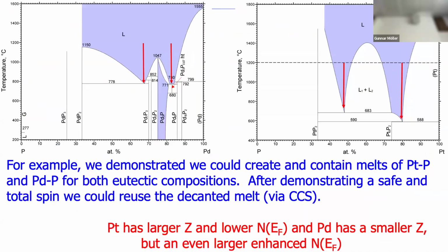Okay, here we have the palladium-phosphorus and platinum-phosphorus binaries. You have two eutectics on either side of either immiscibility or a series of compounds, and we've been able to demonstrate we can work with these. The reason I'm drawing this dashed line at 1,200 is you seal these in amorphous silica tubes. Amorphous silica is only good up to 1,200. Okay, so that's just an experimental reality.